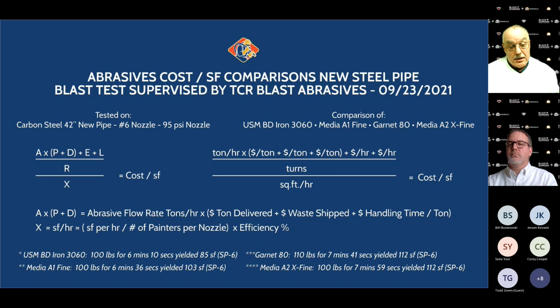So on this test, the ones that we just looked at, there were 4 different materials used. So if you look down at the bottom of the screen, the USM BD Iron 3060, the first one that's asterisked there. So we had 100 pounds of abrasive. It lasted 6 minutes and 10 seconds, and it gave us 85 square feet of SP6 cleaned metal on those pipes that you saw there. So we know exactly how many pounds we used. We know the time that it took to blast that amount of material. And then you've got the square footage. We actually physically measured it.